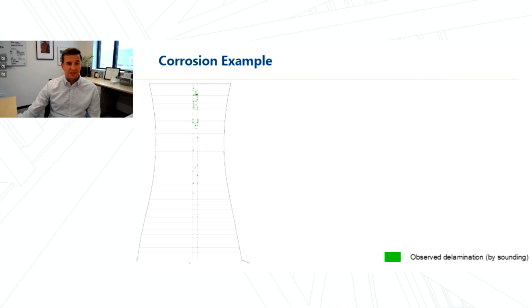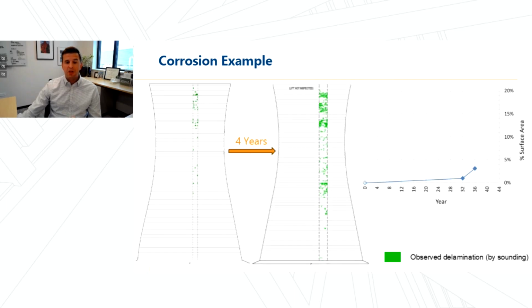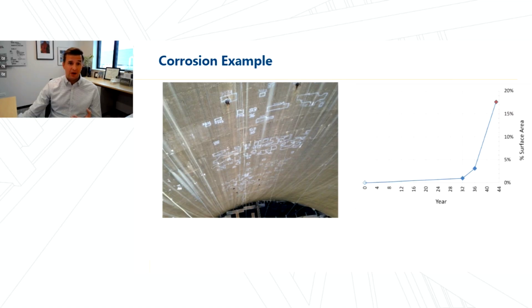Now, to trend this data, a repeat inspection was performed 4 years later and revealed a large increase in the extent of deterioration. If we look at this plot, we see the 0 point, which is the time that the asset was put into service, and then the subsequent back-to-back inspections spaced out by 4 years. And we can see this uptick. In this case, this trended condition in coordination with owner prerogatives resulted in repair actions. And through the completed time of repairs, the trending conditions followed a path of increasing corrosion damage. This is understood and expected when we understand corrosion as a mechanism. So monitoring the asset and capturing repeat data over time is a reliable means of trending conditions in support of predicting future conditions. But we also have predictive modeling tools that can supplement this type of field assessment approach.